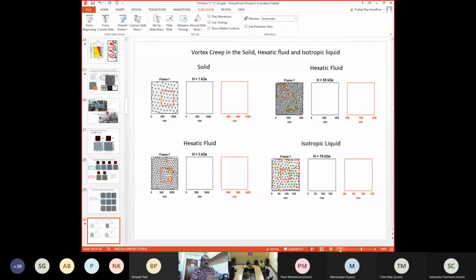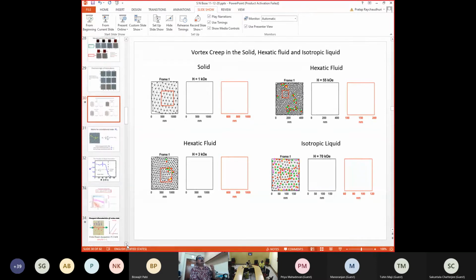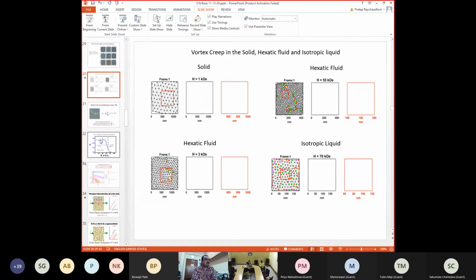I am not applying any drive here. But when I go into the isotropic liquid, which is at 70 kilo Ørsted, now you can see that the motion is completely random, and that is what you expect for an isotropic liquid. So this tells you that we are going from a solid to a hexatic fluid and then to an isotropic liquid. And this is consistent with the hexatic fluid that was predicted by Kosterlitz and Thouless.